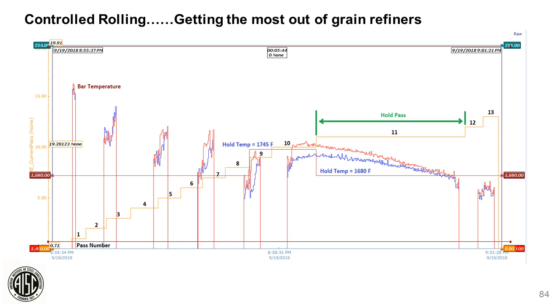But let's look at when we get to about pass 10. Do you see where we have the red line? That's our temperature drop on a flange, and the blue line is a temperature drop on the other flange. Now it's set in the computer, for example, on this particular product, what the hold temperature is. In other words, we're trying to get that temperature down to where those vanadium and columbium nitrides, whichever grain refiner we're using, will precipitate and form and will be able to act as the grain refiners we're intending them to. So this is hooked up to the computers, and that bar will not advance until that temperature is hit. We call this, in this case, the hold pass. We want a certain amount of reduction left while before that bar advances, and it has to be a certain temperature. Next slide.